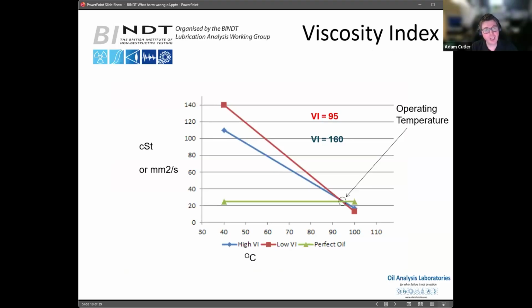So we measure this change over temperature in something called a viscosity index, and that looks at the temperature at 40 degrees Celsius and 100 degrees Celsius. Now, if we just take this example system here, where we've got an operating temperature of, say, 95 degrees Celsius. Now, this could be an engine, for instance. All the oils give the exact same target at operating temperature, so they're equally as good as far as the film thickness at operating temperature. But if we take this oil and extrapolate off here, it's going to be very thick at cold temperatures, whereas this one's going to be very stable. This is technically the perfect viscosity index. It's like infinite here, but this is unrealistic. You'll never get this, but you try and get as close to this as possible.